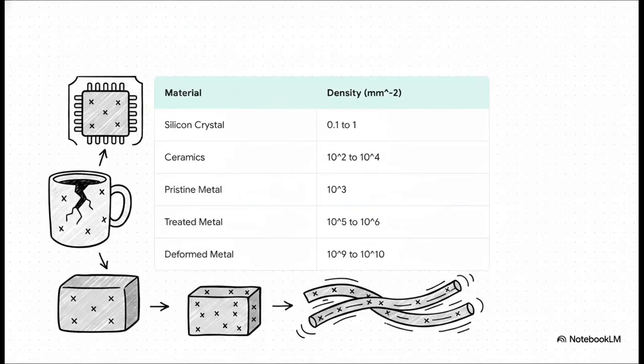It's wild. Comparing these numbers across different materials really puts the whole thing into perspective. For instance, silicon single crystals, those pristine materials we use to make our computer microchips, have incredibly low densities. We're talking maybe 0.1 to 1 defect per square millimeter. Ceramics sit a bit higher, somewhere between 100 and 10,000. But metals? Even a carefully solidified pristine metal starts out at 1,000, and heavily deformed metals, as we just saw, skyrocket into the billions. This massive density of mobile defects is exactly why metals are so forgiving and bendable, while your ceramic coffee mug or a silicon wafer will just catastrophically shatter under stress.